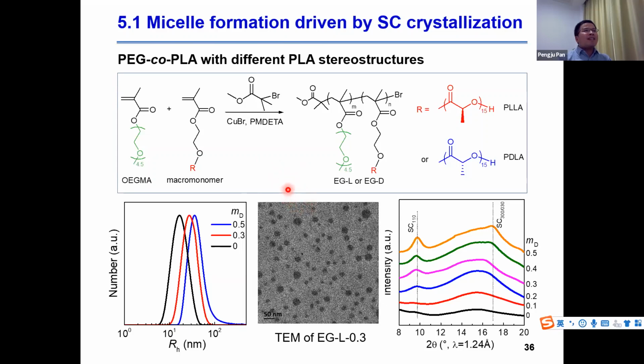However, the micelle size increased when the L copolymer and D copolymer are mixed. From the XRD plot of the freeze-dried micelle, we can see the mixed copolymer forms crystalline micelles because of the stereocomplex crystallization between PLLA and PDLA blocks.